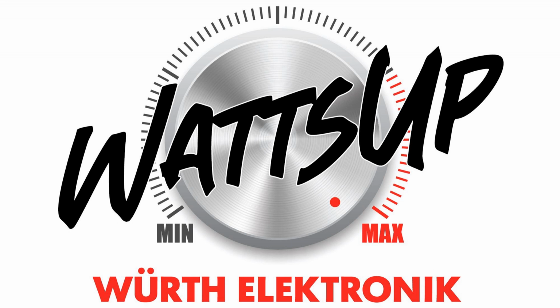So, by adding multiple turns through the ferrite, you are increasing the impedance, but you're shifting the frequency range because you're adding capacitance. So this second curve shows impedance you will get if you do two turns through the clamp-on ferrite. This third curve shows impedance with three turns. So as you can notice, a higher impedance but shifted frequency range.